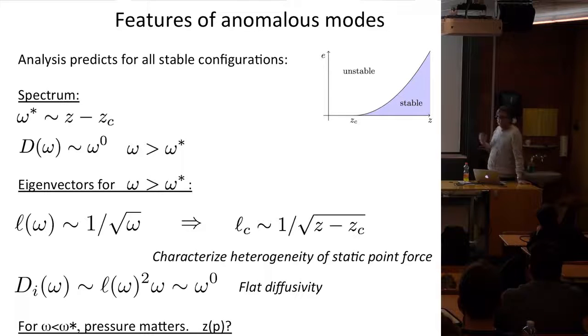Okay, so you can think about stability, but those techniques also give you much more. They give you the density of states and some aspects of the eigenvectors. So here I'm just going to summarize what you can get. For example, with those methods, you do get this frequency scale, like seen numerically, when you approach this unjamming transition, when the packing has a lower and lower pressure. You find that the density of vibrational modes has to be flat above this characteristic frequency. But you can also access some properties of the eigenvectors.